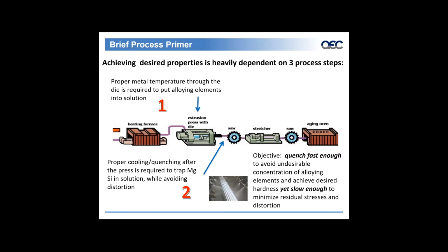Okay, so right after the extrusion press, we took a billet, we brought it to the appropriate temperature, we took into consideration the die design and the metal flow that goes through the press, we extruded at the proper rate. Now we must quench that product. And the graph that we showed earlier that was relative to the mag and silicon represented really three different layers. 6060, 6063, this process here can be achieved by an air quench. So the distortion of the product is much less.